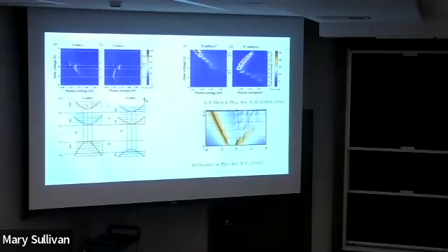So if you have these Landau levels, right, with a spacing of roughly 4 milli eV, or on the order of 10 milli eV, now, in the presence of that Landau level, what's the exciton picture? Your exciton binding energy now, especially in the intrinsic region, is on the order of hundreds of milli eV. It's many times this Landau level spacing. How do you think about this? You cannot think about it as a free electron and a free hole here, right?